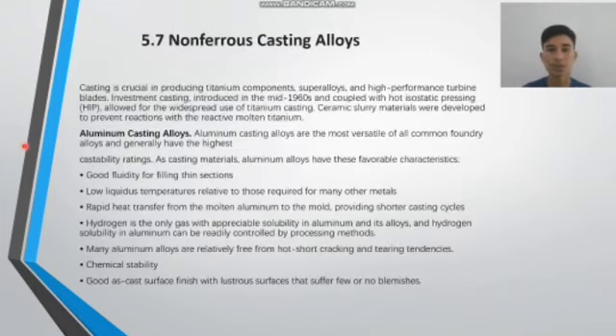Next, 5.7 Non-ferrous casting alloys. Casting is crucial in producing titanium components, superalloys, and high-performance turbine blades. Investment casting, introduced in the mid-1960s and coupled with hot isostatic pressing, or HIP, allowed for the widespread use of titanium casting. Ceramic slurry materials were developed to prevent reaction with the reactive molten titanium.